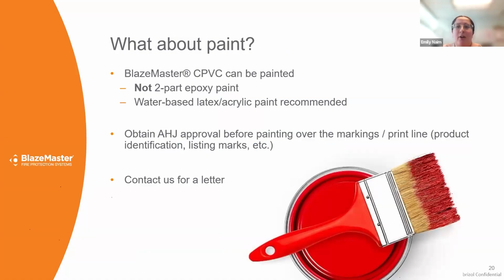And now a common question we also get asked about is, is CPVC compatible with paint? And yes, it is. So we recommend any water-based paint or acrylic paint, but most other paints are fine, like spray paint, oil-based, latex. Just apply a thin coat to it, avoid puddling around the joints, but there is an exception to this. The only paint that is not really compatible with CPVC is two-part epoxy, because just like polyurethane foam, CPVC is not compatible with part A or B of the epoxy on its own. So if you have to use it, just keep the coat thin and make sure there's no excess. But at that point, it's honestly easier to stick to a one-part paint.